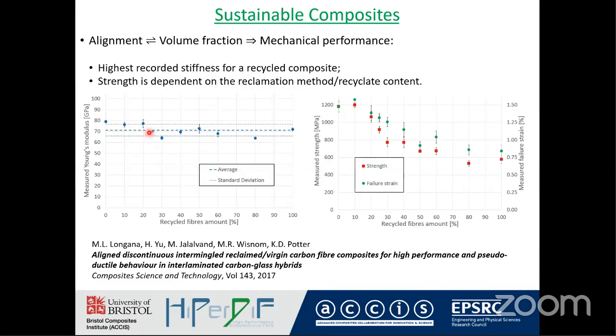So in this case, the stiffness is not affected by increasing the recycled fiber content. There is a diminution in the strength and failure strain, as you can see, as the recycled fiber content increases. But this again underlines the need for introducing recyclate in which the fiber properties have not been degraded during recovery.